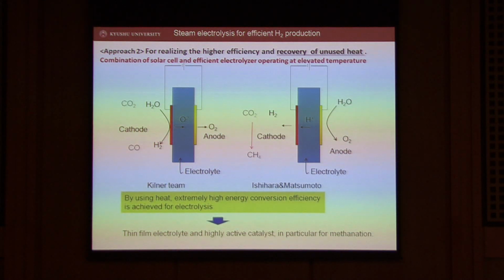If we combine this system with CO2, the obtained product is slightly different. In the case of oxide ion conductors, we obtain CO and hydrogen, and then we can synthesize higher hydrocarbons by Fischer-Tropsch synthesis of the obtained synthesis gas. But in the case of proton conductors, we can directly change carbon dioxide to methane. Therefore, this kind of reactor is very interesting for recycling hydrogen and recycling CO2.